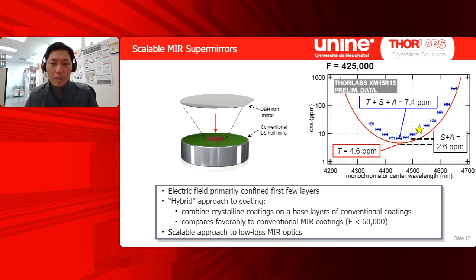So to give you some context, the highest finesse mid-IR mirrors at this sort of wavelength we've found in the literature is about 60,000. So we're doing fairly well in comparison to the literature. And to demonstrate some application, and this will be the last point of the talk here, you can see there's a star just past 4.5 microns. It turns out there's some nice absorption lines we can look at there.